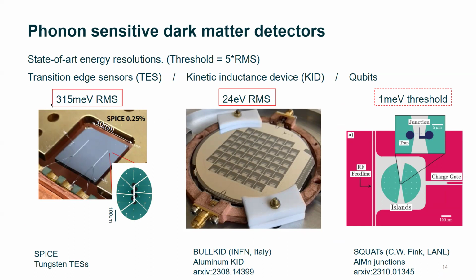So here are the numbers. We already achieved around 300 meV RMS in this device. And this KID device, this is more or less the leading result from this group. It's 24 eV. It's far behind the TESs because of the phonon collection efficiency problem. And of course, this qubit is only a proposal, but we are very interested in looking forward to the result. As I said, you can keep going into smaller volumes, keep going to lower TCs, and try to improve the energy resolution.